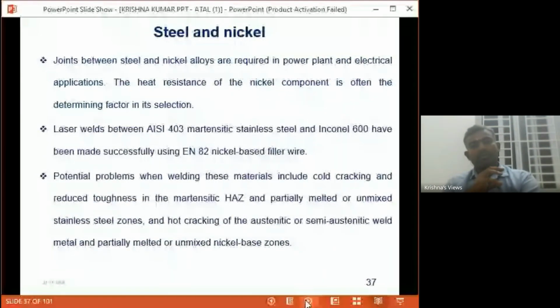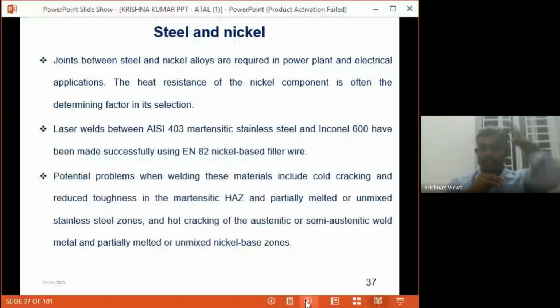Then steel and nickel. Joints between steel and nickel alloys are required in power plant and electrical applications. The heat resistance of the nickel component is often the determining factor in its selection, and also the conductivity. Welds between, say, 403 martensitic steel and Inconel 600 have been made successfully by using ERNiCr-3 nickel based filler wire.